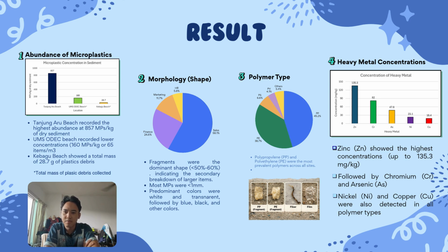Looking at the abundance of microplastics, Tanjung Aru recorded the highest abundance at 857 microplastic particles per kilogram of dry sediment, while UMS ODEC Beach showed lower concentration. Kebago Beach also recorded a measurable amount of plastic debris. The higher abundance observed at Tanjung Aru may be influenced by greater human activity, tourism pressure, and the accumulation of waste material in the coastal area.